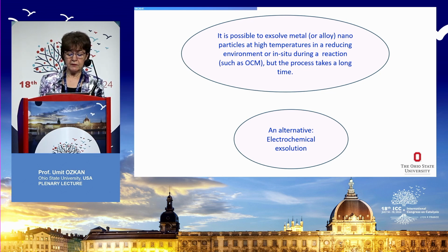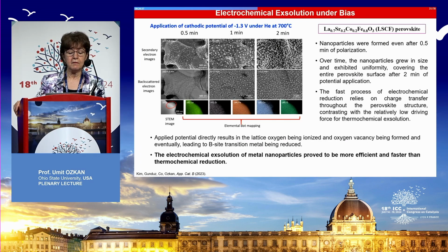An alternative is electrochemical exsolution. What we have found out is that by applying a cathodic potential, within minutes, like less than a minute, we start having exsolution of metallic particles to the surface.